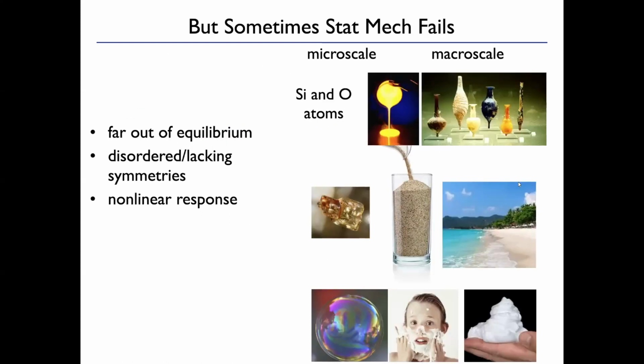But there are lots of problems where statistical mechanics has failed, or at least has not given us as much as we would like. And so examples of these are ones that have preoccupied me for a long time, with my collaborator, Sid Nagel at the University of Chicago. So for example, if you start out with silicon oxygen atoms to make silica glass, or you could have systems where you have grains of sand, which are usually actually glass beads, so they're spherical, which you pour them in. You can pour them and they behave like a liquid, or if you walk on the beach, you don't sink through as you would sink through a liquid, but it actually supports your weight like a solid.